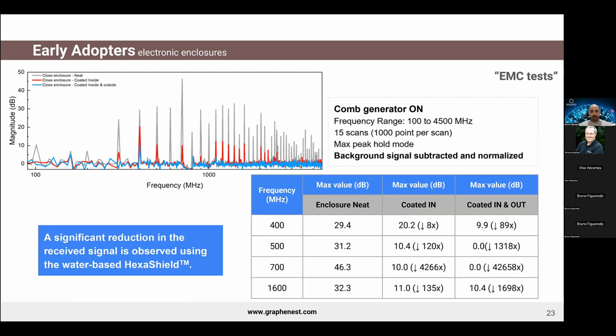But the real test was then made on 3 different enclosures. In gray, you can see the measurement made with the inverter box completely neat, so no coating, only the PC ABS. In red, the spectrum is the one from the inverter box painted only inside, and the blue one, the inverter box painted inside and outside. In all of them, we can see the periodic signals from 100 megahertz to 4.5 gigahertz.